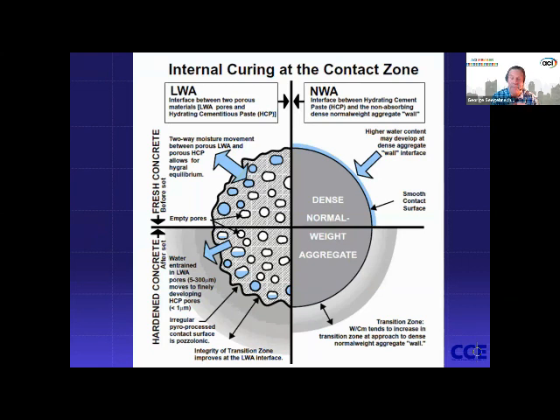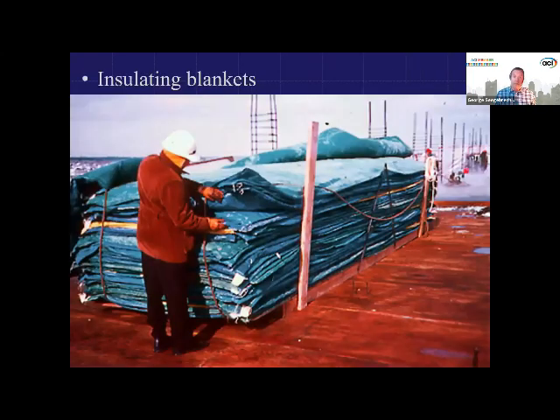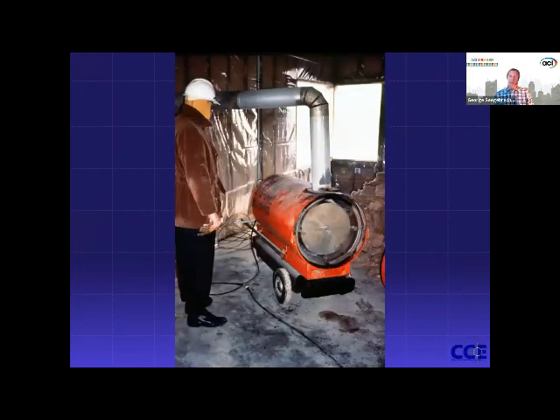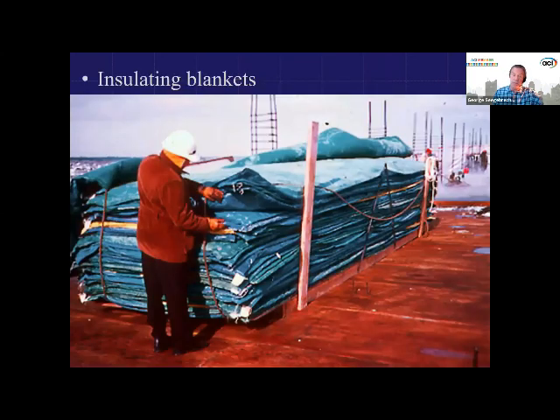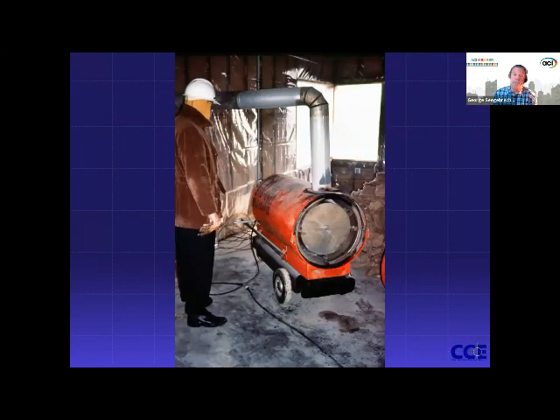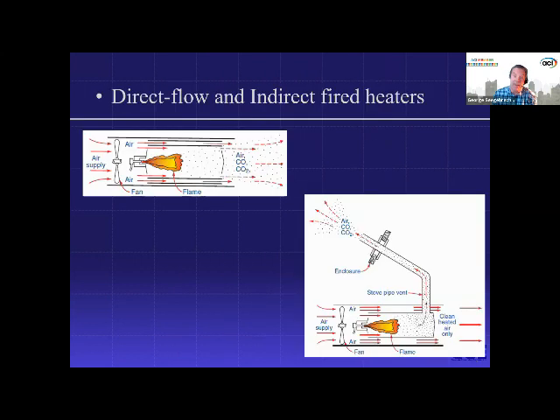It's in combination with. Those are the insulating blankets that I mentioned before. If you're going to use heating, that I mentioned before about keeping the plastic down and keeping it flat. If you're going to be using heaters, use indirect heaters. Here's a schematic from PCA versus a direct fired heater, which sends CO2 into your work area. And when it comes in contact with fresh concrete, it will carbonate the surface and cause dusting. Not the dusting you clean up with the dustpan. It's a surface that is soft and carbonated, and you don't want that. It's a pain in the neck.